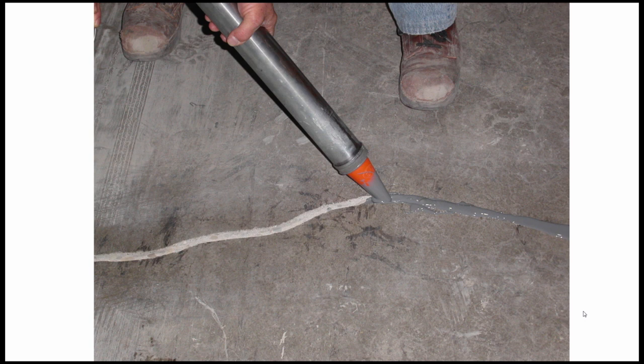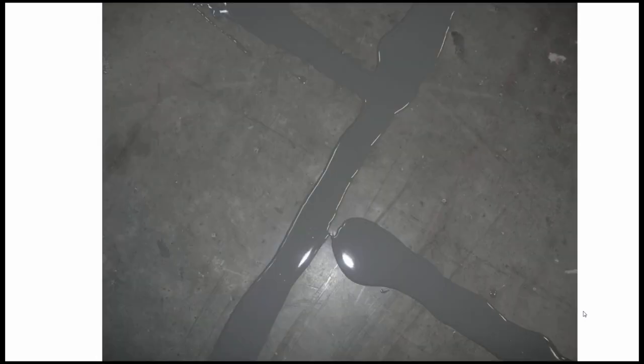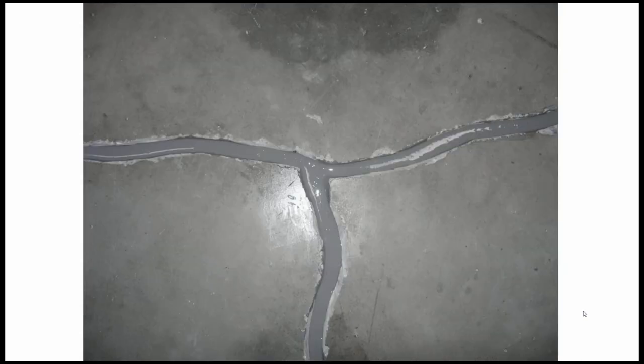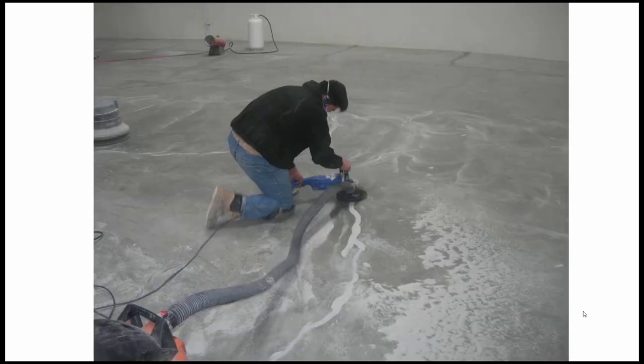Well, here's an example of the guy filling it up with the semi-rigid material. And as I mentioned, you want to overfill it so you can get a nice clean surface at the top once you shave it off. If you don't use the sand, sometimes the material will want to fall back down in there and run down into the crack. Or sometimes, actually frequently, this happens even if you do use the sand. So you'll need to top it off with some more material, or you can come back the next day and add material. When I go around warehouses and big box stores like Home Depot or Walmart, I often see this condition where the material ran down low and they didn't get it nice and flush.